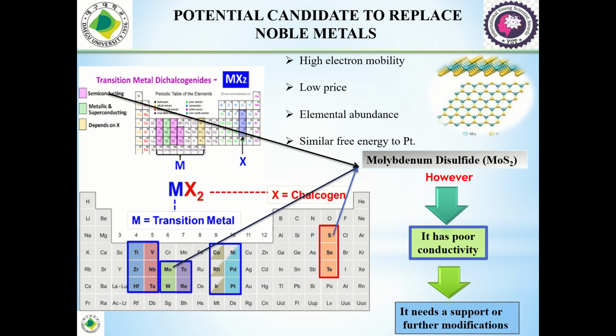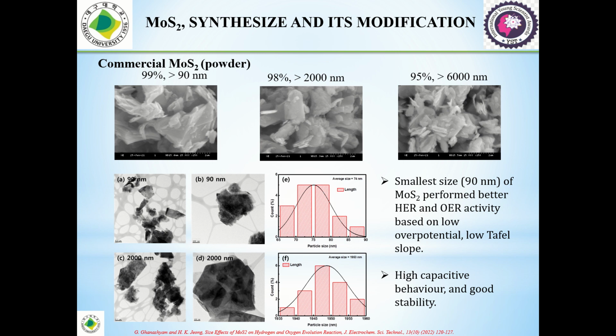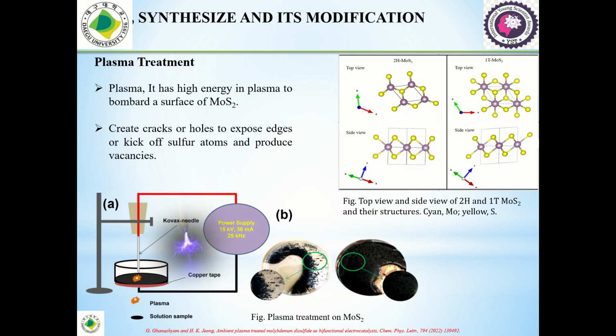However, MoS2 in the pristine structure has its edges covered by inert sites, and it has very poor conductivity. So it needs supportive materials or further modification. In the beginning, we chose commercial MoS2 of different sizes, and we studied and compared their performance. And we also modified the commercial MoS2 by using different types of techniques like plasma treatment, heteroatom doping, and so on.